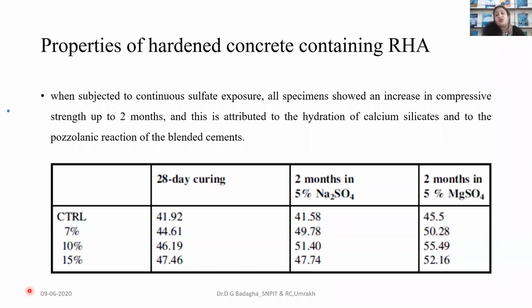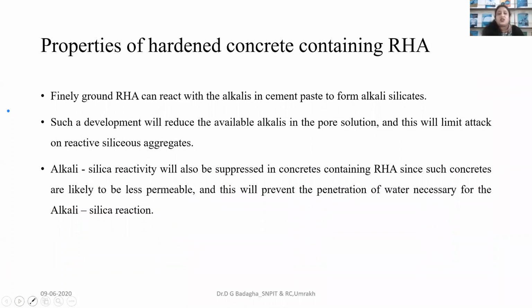After 2 months of curing in 5% Na2SO4, you can compare the strength with control concrete. That CTRL is the control concrete, meaning 100% cement. Here 7%, 10%, 15% replacement with cement. Okay, so here you can easily understand that if we use that RHA in our concrete, definitely the performance will be good in RHA concrete, and that's why we came to the conclusion that yes, RHA is advisable to use in concrete.